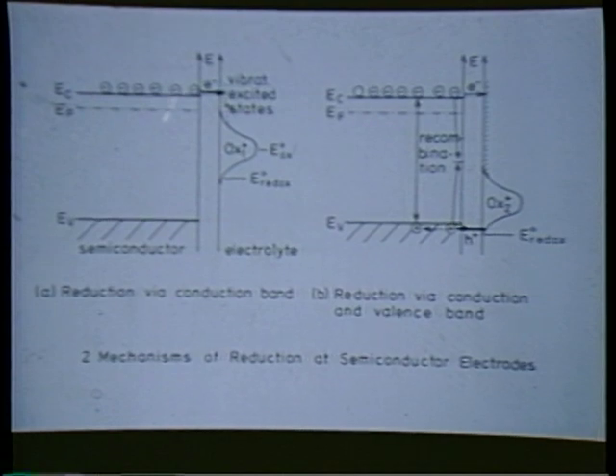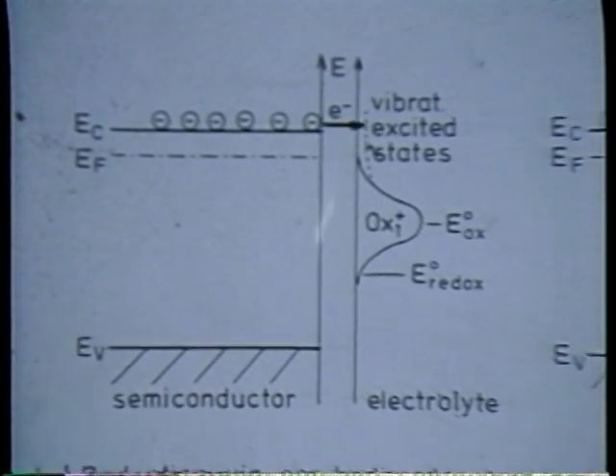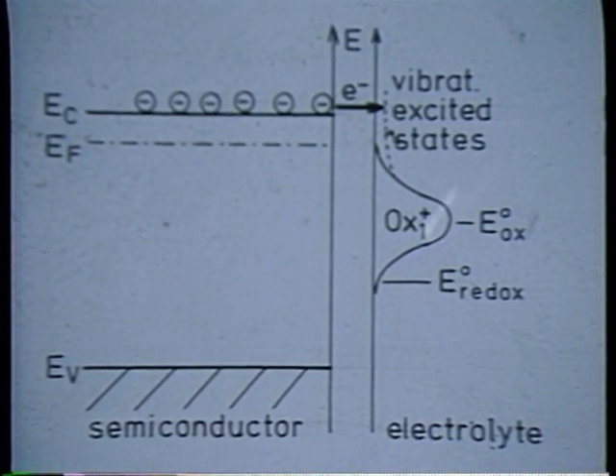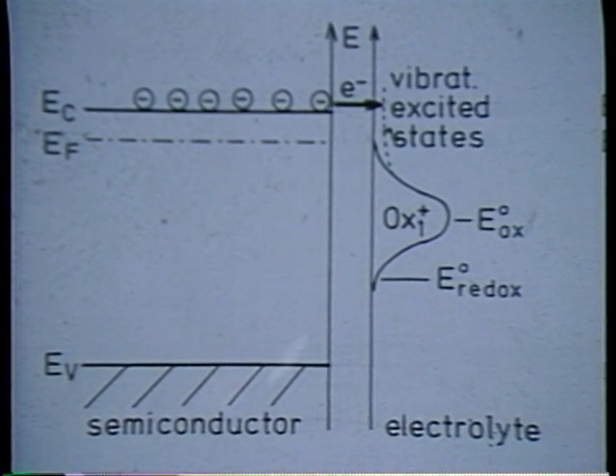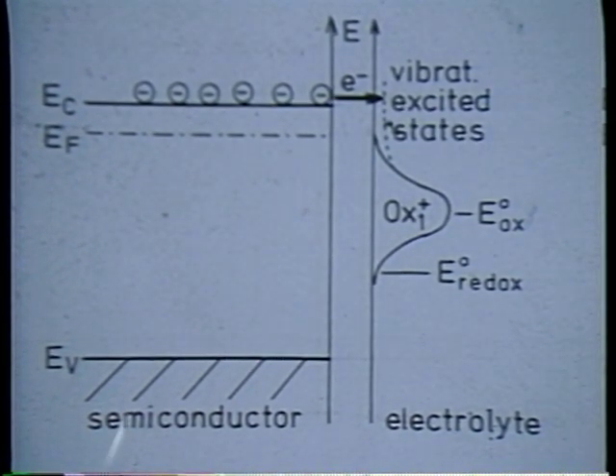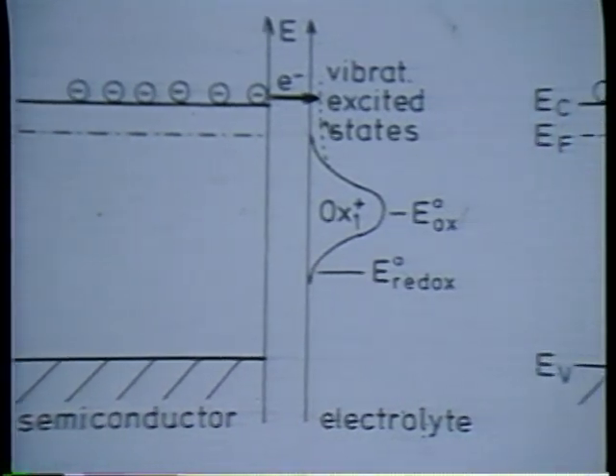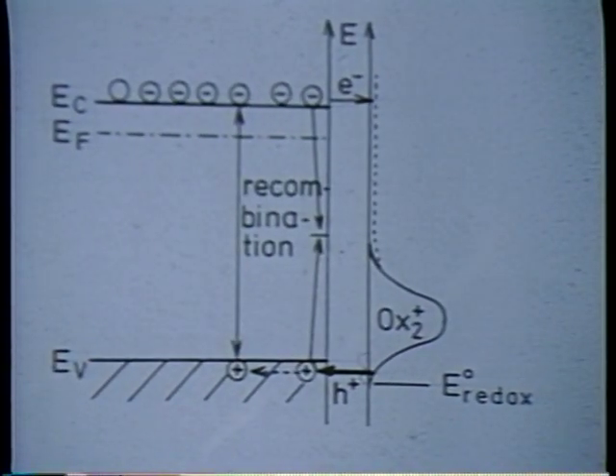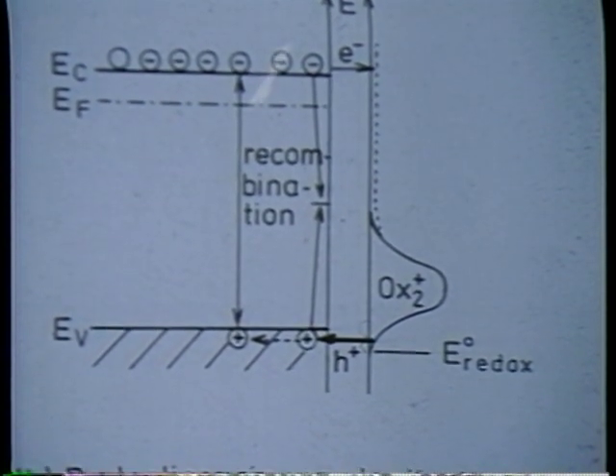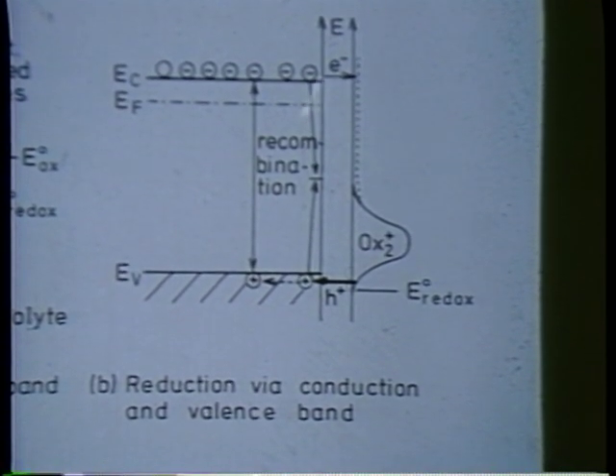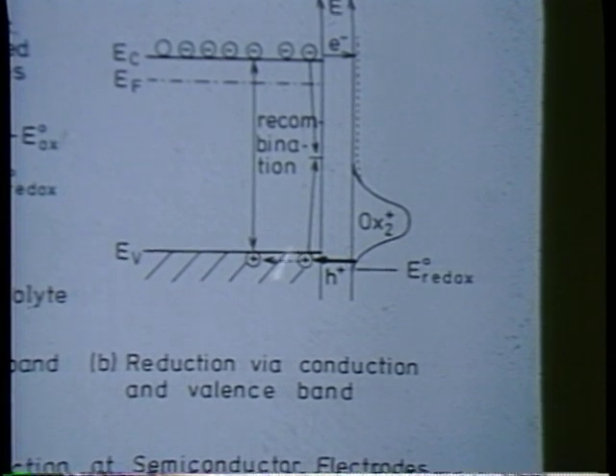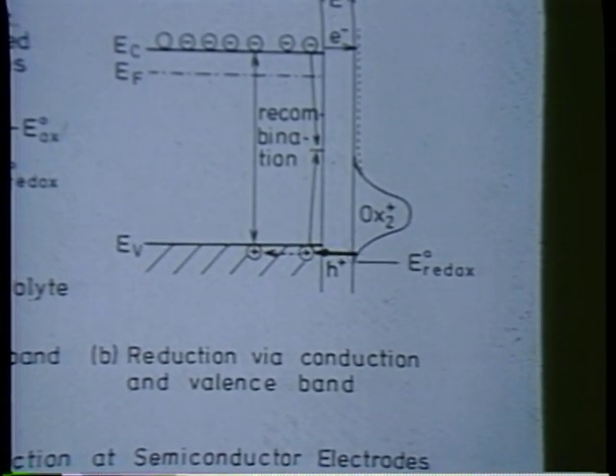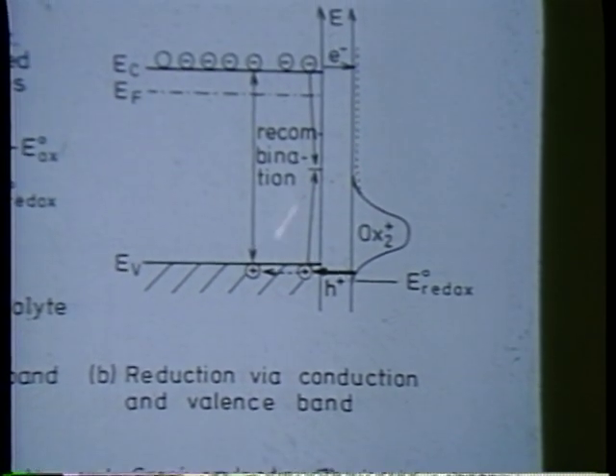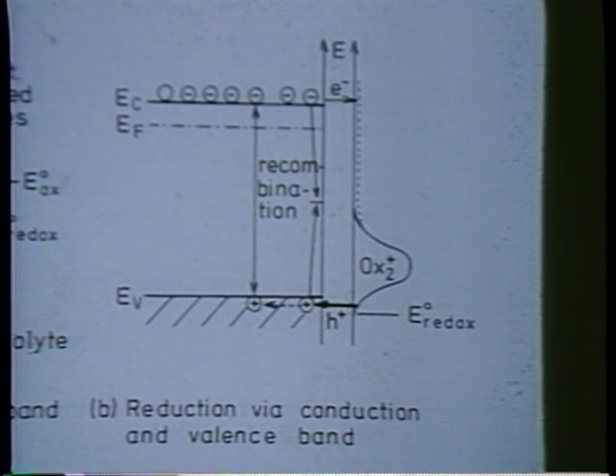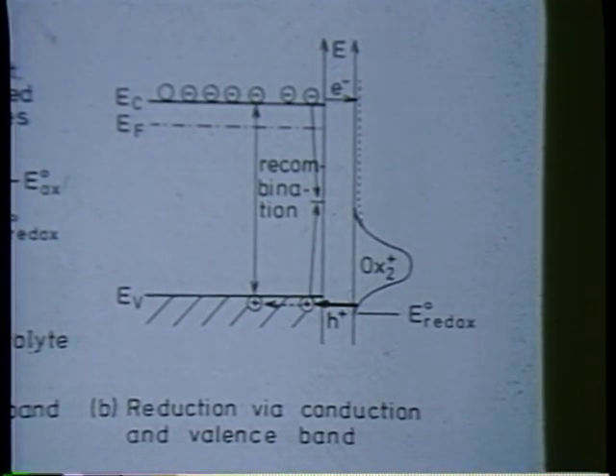Now, if we have oxidized species in the region, which has energy levels above the valence band, no hole injection is possible. Reactions will only go via electrons from the conduction band, and if you have enough electrons, they will find their way to the oxidized species. If we have this situation, where the species is much more oxidizing and can inject holes, the question is, if we have electrons available on the surface, do they react directly from the conduction band, or do they primarily react with injected holes? And if the latter is the case, you would expect that now part of the recombination between electrons and holes might be radiative, and you might see luminescence,